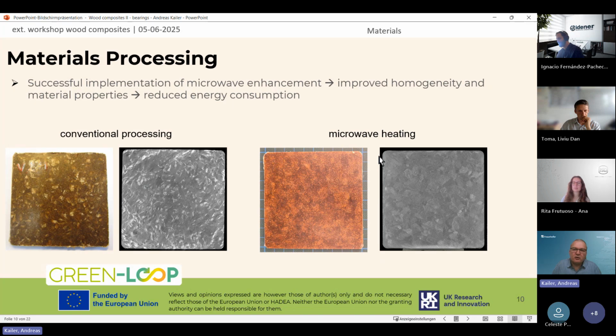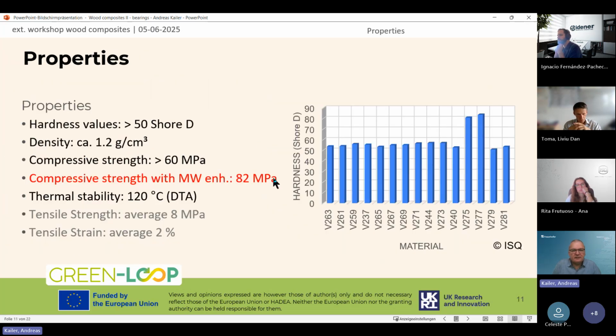Livio also talked about this microwave enhanced processing, and finally with this processing also we got a good material homogeneity and very good mechanical properties, and finally also good friction wear properties, as you will see. The mechanical properties here, in short, we have had hardness values larger than 50 Shore hardness, density 1.2 grams per cubic centimeter, compressive strengths between 60 and 82 megapascals, and the thermal stability up to 120 degrees Celsius. So very good properties.